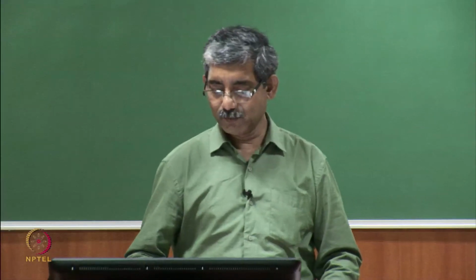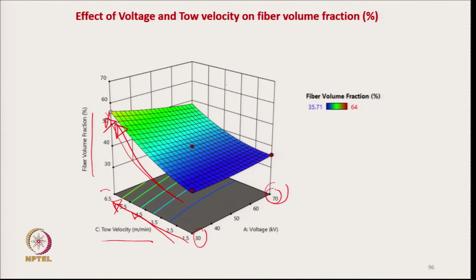Similarly, at a higher level of tow velocity, the effect of voltage, the effect of charging, is prominent, it is significant, but at a lower level of tow velocity the charge effect is not that significant, it is almost horizontal, okay. There is no change.